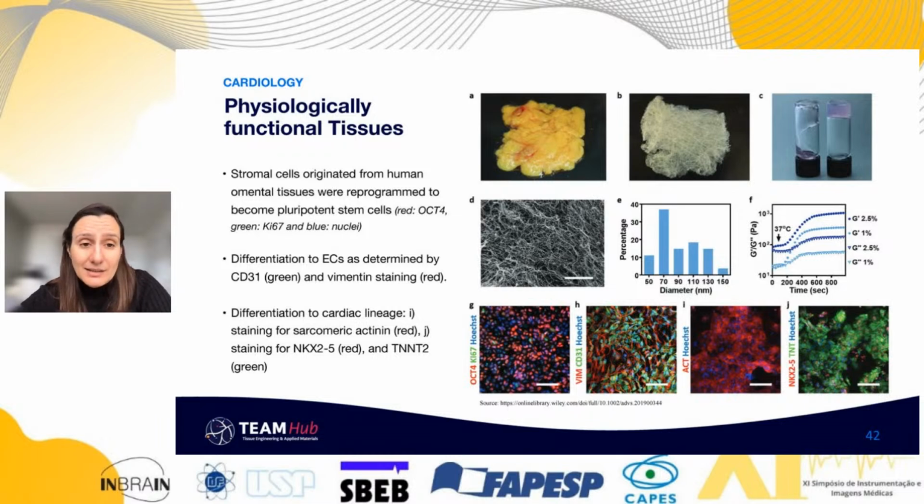So they took a little bit of tissue, and from this tissue, they isolated some stromal cells. This is basically fat tissue. They extracted the cells, and they were left with the ECM, the extracellular matrix. All these proteins eventually got transformed, quote unquote, into a bioink. You can do some chemical processes where you can transform this carcass of the tissue into some sort of a gel. And from this gel, you can use it as a basis for bioprinting whatever you want.